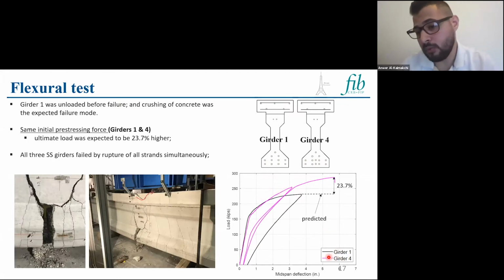Investigating girder 1, which is the control girder, with girder 4, they had the same initial pre-stressing force. We can see here that the flexural behavior of the control girder and the one with the stainless steel strands is different. The control girder was not loaded up to failure. It was unloaded before failure. It was saved for a future shear test. But the stainless steel girder was loaded to failure.